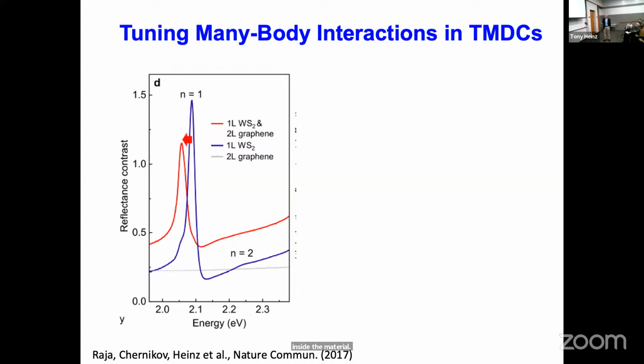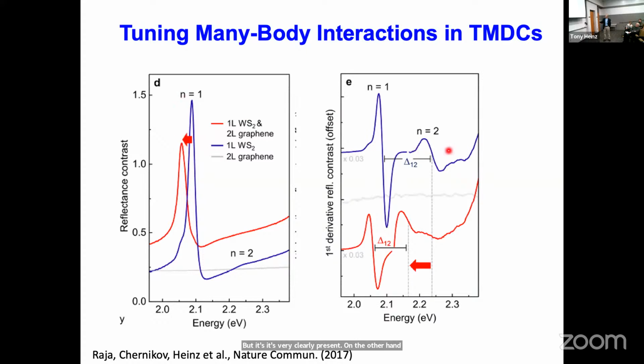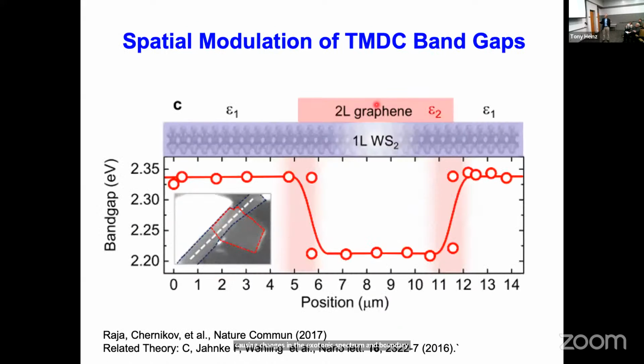On the other hand, if you look at the excited state, which is this feature, it actually shifts by quite a lot, by about 100 millielectron volts. Pretty big scale in the energy change just by putting this external material. And it's not that you're changing the chemical bonding or anything of that sort. In the language of condensed matter physics, we'd say you're modifying the many-body Coulomb interactions in the material, and that's causing changes in the excitonic spectrum and band renormalization. So this is actually kind of an interesting situation.